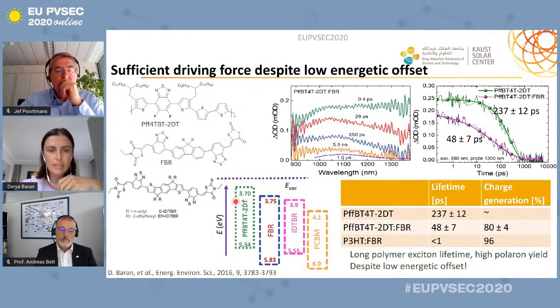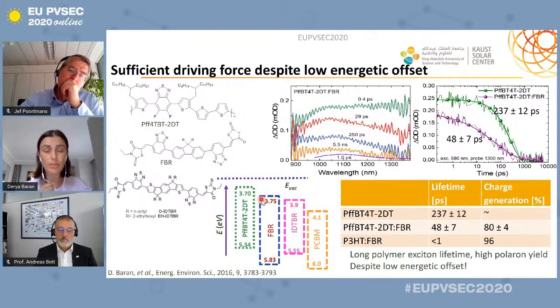So the particular case here, as you see, the electron affinity difference between these donor and acceptor is quite small, and smaller than 0.3 even. And then, as I said earlier, it has been shown that the exciton dissociation is not limited to this 0.3, but the charge separation was.